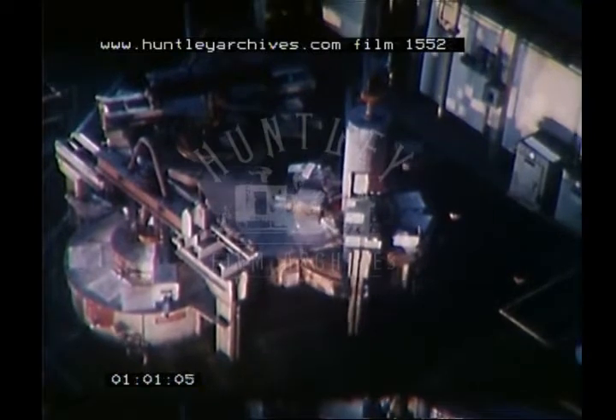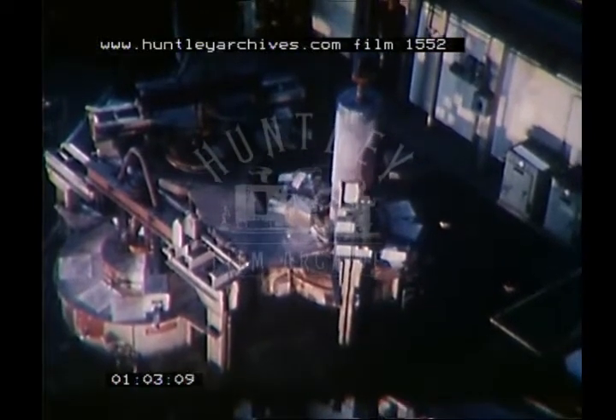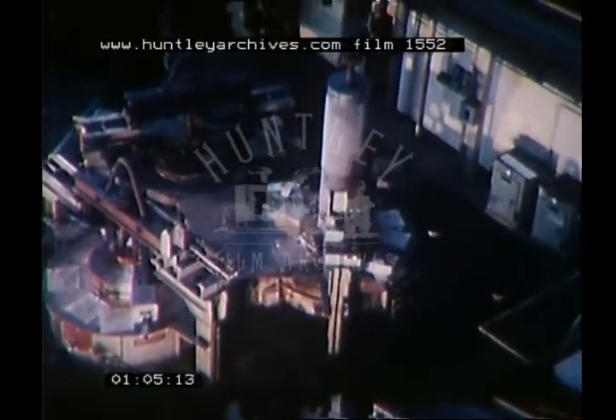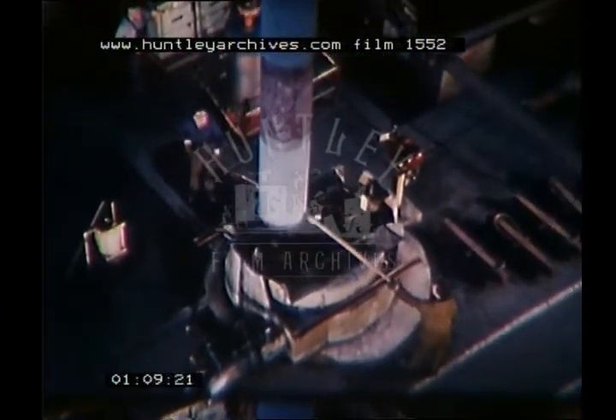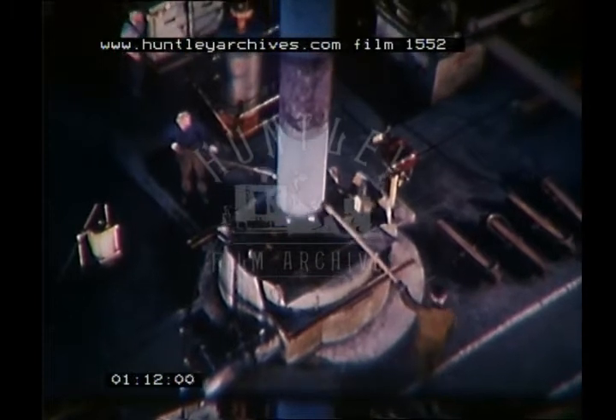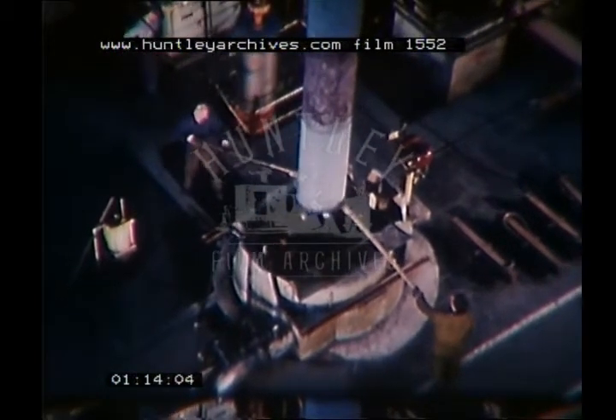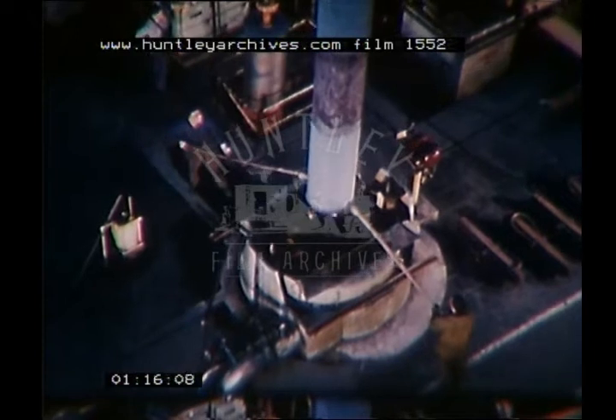Heating for the hardening process is carried out in vertical furnaces specially designed to ensure uniformity of temperature. The journals are carefully protected to prevent their being hardened when the barrel of the roll is quenched. On withdrawal from the furnace, the roll is transferred to the high-pressure water spray tank for quenching.